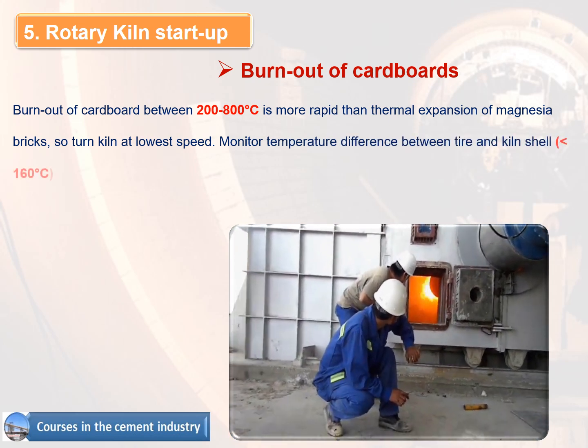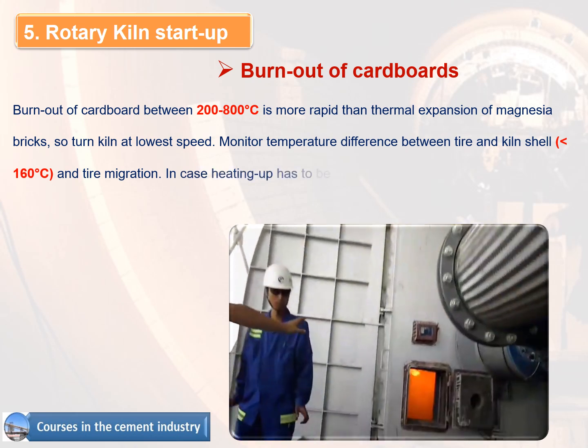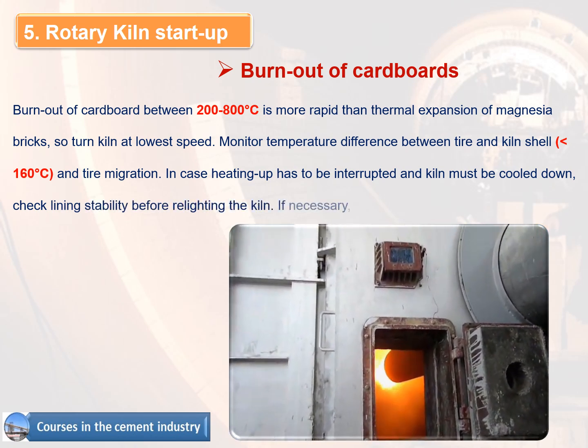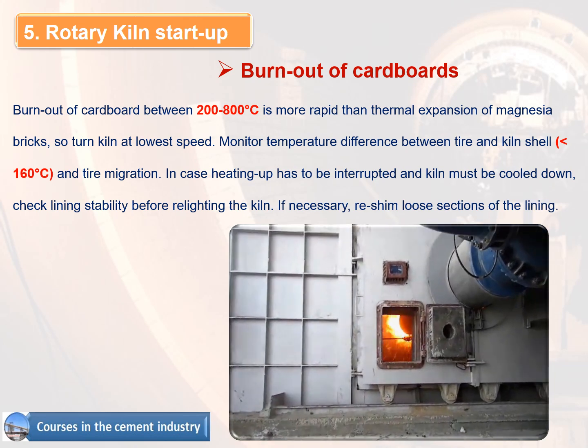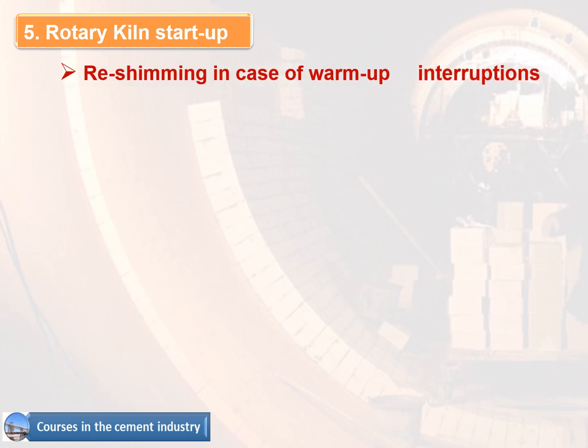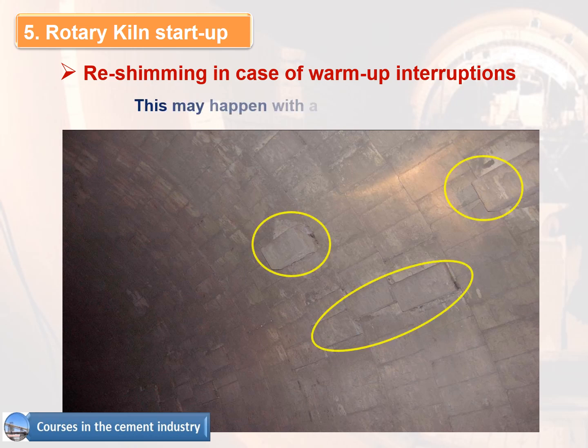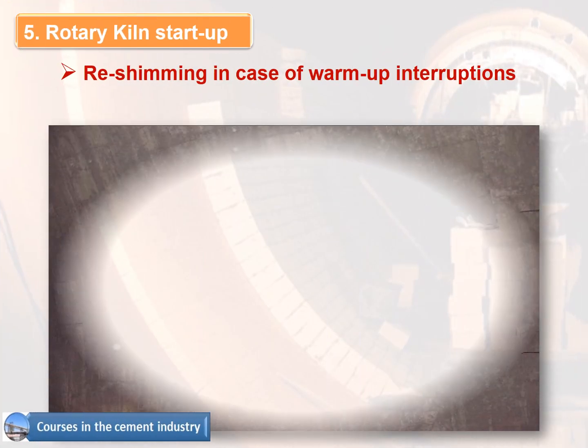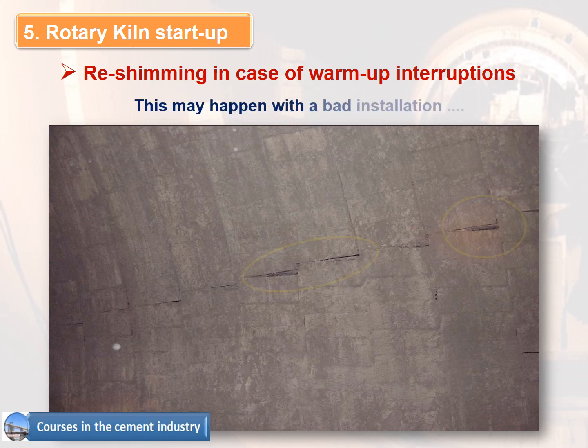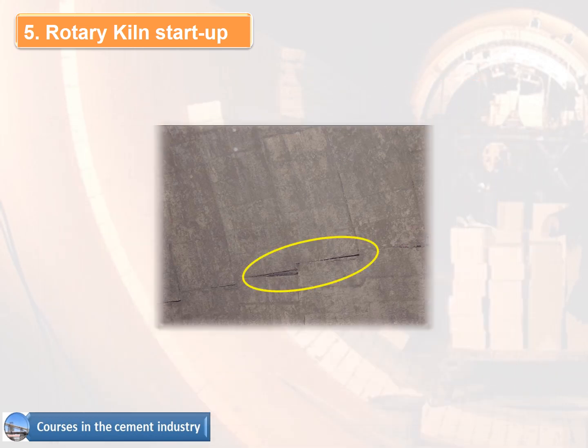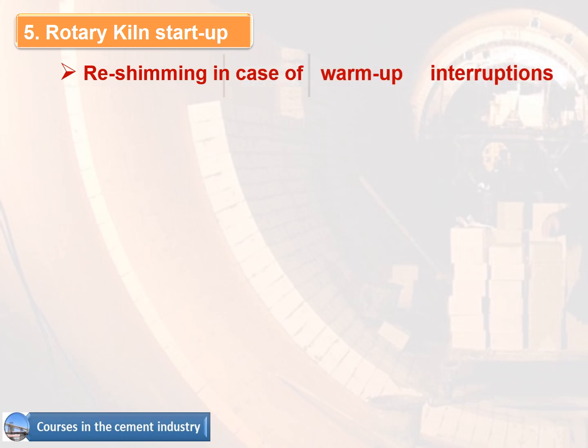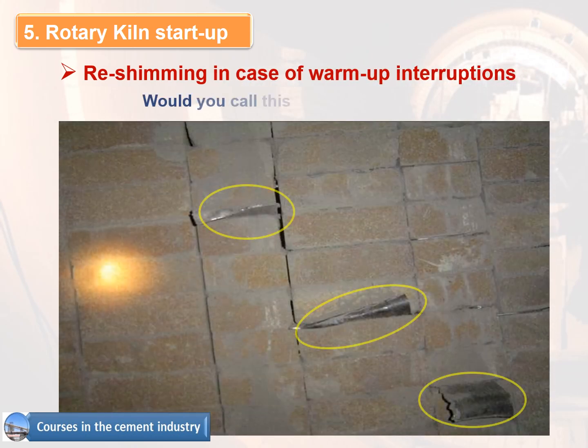Monitor the temperature difference between tire and kiln shell, less than 160 degrees, and tire migration. In case heating up has to be interrupted and the kiln must be cooled down, check lining stability before relighting the kiln. If necessary, reshim loose sections of the lining. Reshimming in case of warm-up interruptions. This figure shows what may happen with a bad installation. In this figure, would you call this correct reshimming?